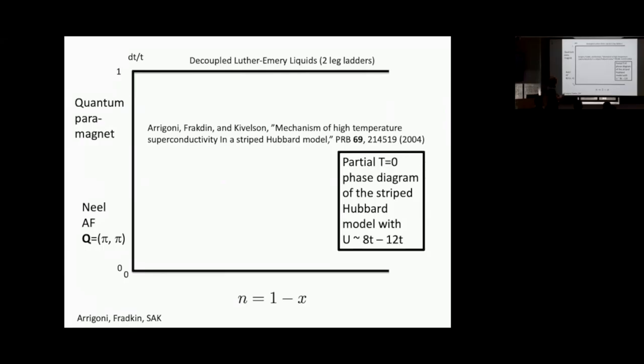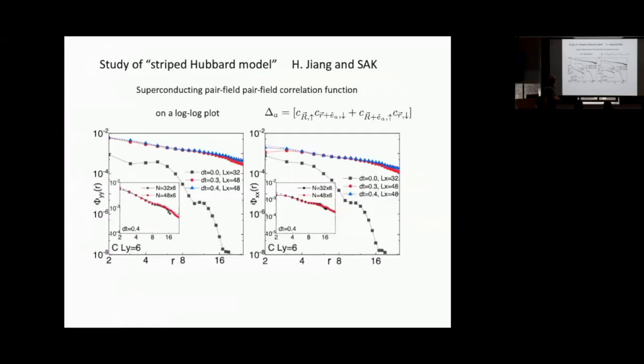What Eduardo Fradkin, Enrico Arrigoni and I did was to analyze what happens as you move off of this top of the phase diagram. And what we found was that in some range of doping, you form a superconducting state, and in some other range of doping, you form a charge density wave state. Actually, it's a checkerboard charge density wave state, so it's not one that adiabatically continues to the charge density wave state that's seen at small dt. So we decided to explore this by DMRG.